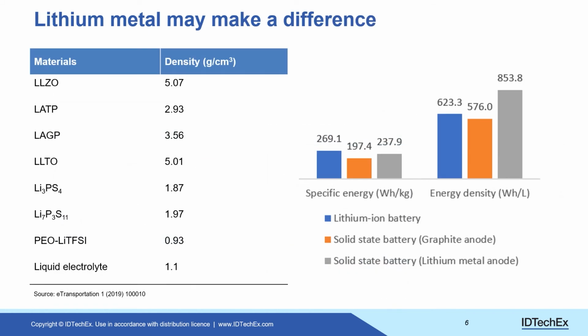Here we show you this table with the most common solid-state electrolytes and their densities, with a comparison to the liquid counterpart. As you can see, most of the solid-state electrolytes have a density higher than the liquid electrolyte. That means if you just replace the liquid electrolyte with the other electrode unchanged, you may not necessarily have the benefit of the higher energy density. So we did a calculation with an NMC811 cathode and a 40 micrometer electrolyte. You can see the result on the right-hand side just for LLZO, the garnet one.